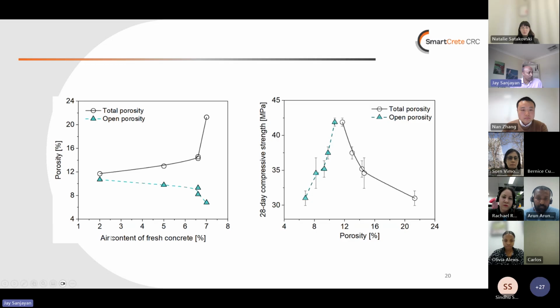You can see when the air content of the fresh concrete increases, that is with increasing air content, the total porosity, which is the top curve, increases, but the open porosity, which is only part of the total porosity, is actually decreasing. Again, if you look here, the curve with the circles, which is the total porosity, increases and the strength decreases. But at the same time, the closed porosity increases. So this is an anomaly we found, and that might give some explanation.